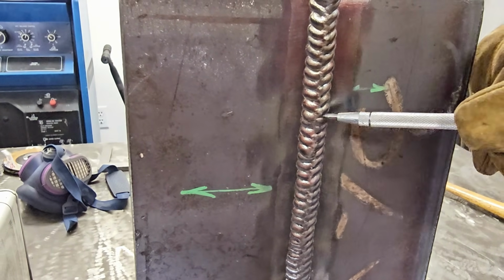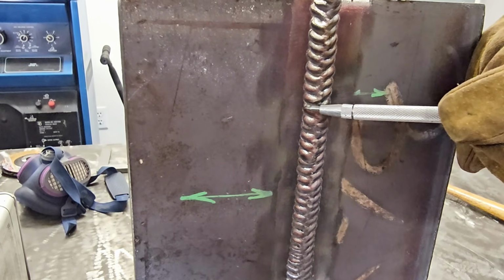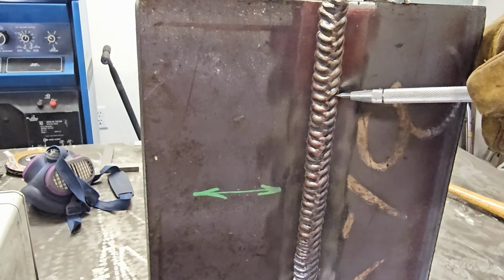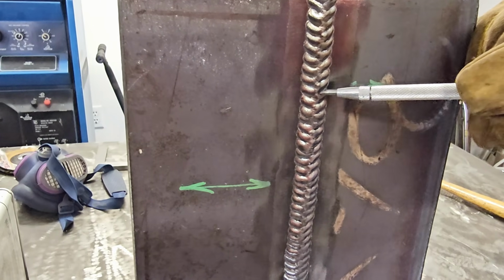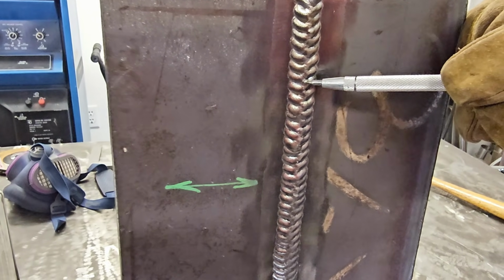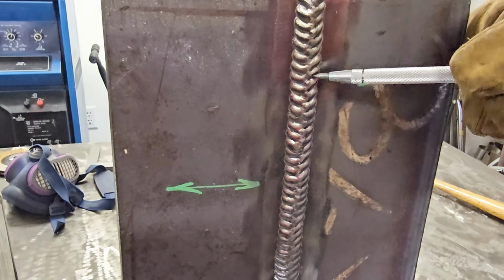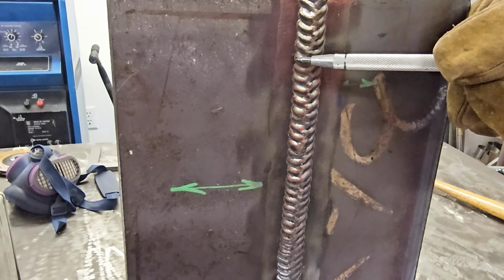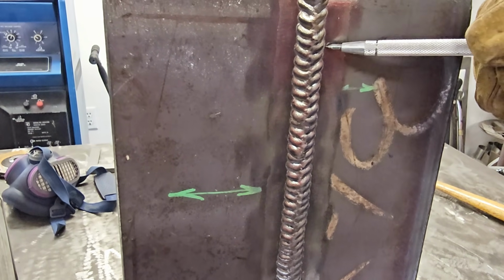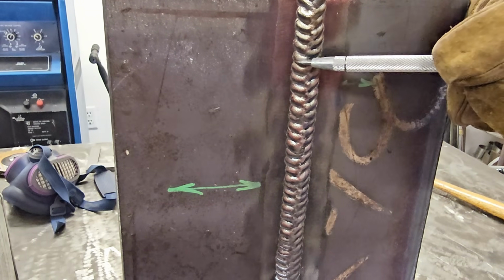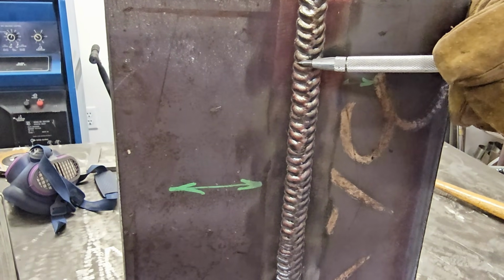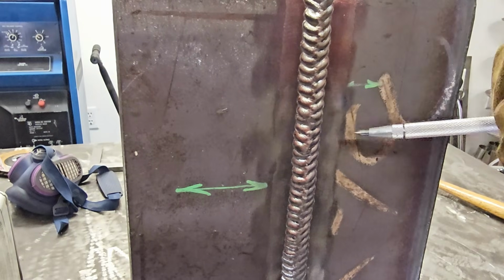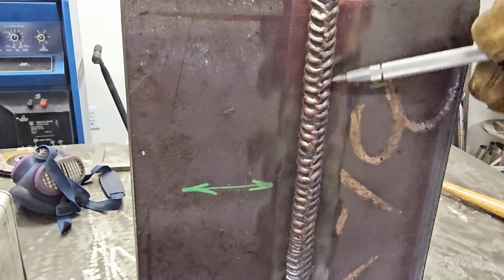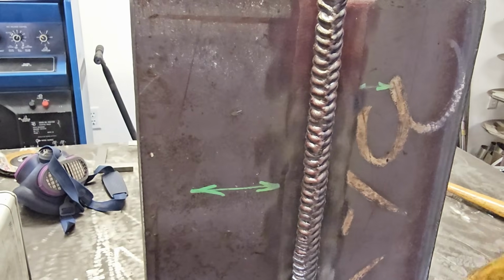Also, watch your Z-weave pattern as you go side to side. Make sure that it's close enough together to where it's all bleeding together and filling in and tying in. If you go too far ahead, meaning you advance too much on each part of your Z-weave, then you'll leave some little areas in between that can give you trouble on your bend test. So this is pretty ideal for what we'd like to see on our cap.